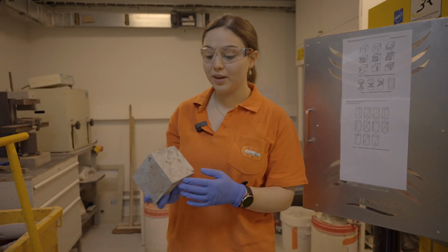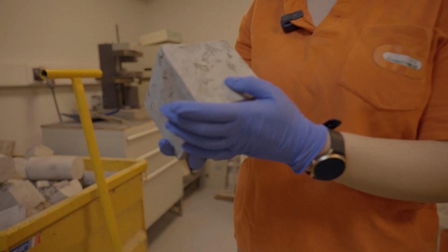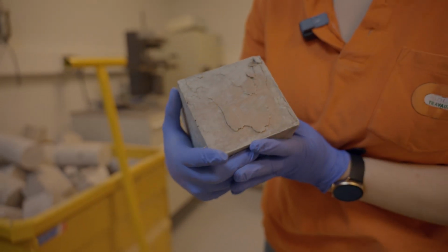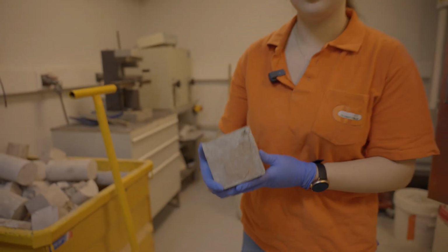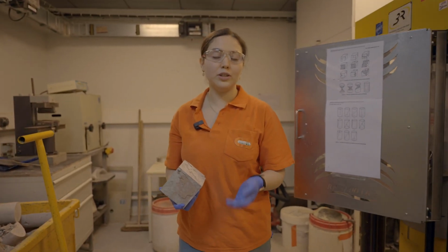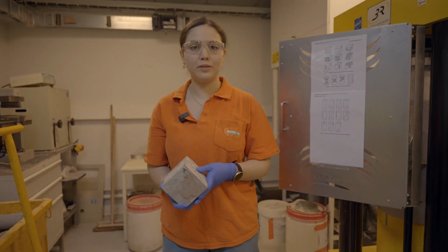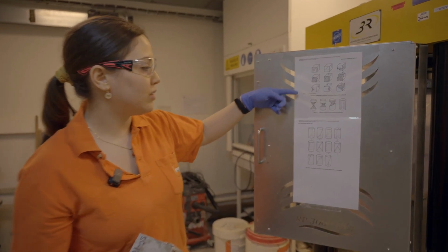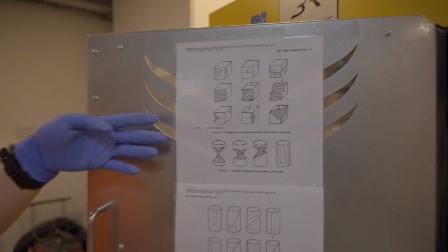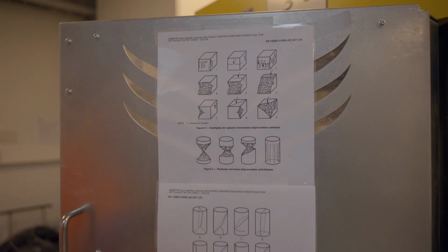After the specimen breaks, we check the fracture to see whether it is proper or not, in order to confirm that the strength we obtained is indeed correct and that there was no defect in the making of the specimen. Then we can refer to this diagram to determine whether our specimen is acceptable or not.